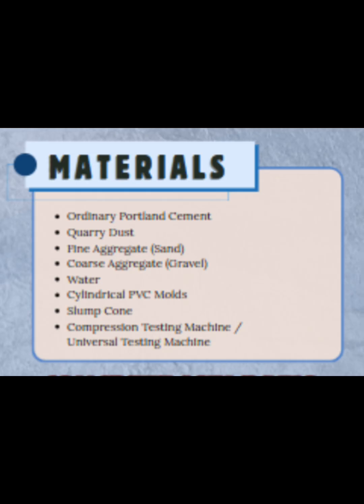For this study, we used the following materials: ordinary Portland cement, quarry dust, fine aggregate or sand, coarse aggregate or gravel, water, cylindrical PVC molds, slump cone, and compression testing machine. These materials were used to produce both the control mix and the experimental concrete mixtures.